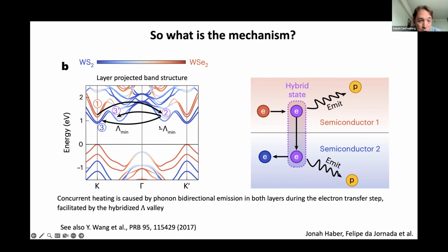However, what you do see when you compute these band structures is that there's another part of the band structure. This is called the lambda valley, or also sometimes called the Q valley of the structure. And this structure is actually hybridized. This whitish, grayish color here is indicating that this has significant contributions from both WS2 and WSe2. So the proposed hypothesis here is that there is initially very fast coupling to this lambda valley. This hybridized state then can couple directly, through the emission of phonons, into both layers simultaneously, and couple directly into the top semiconductor and the bottom semiconductor.